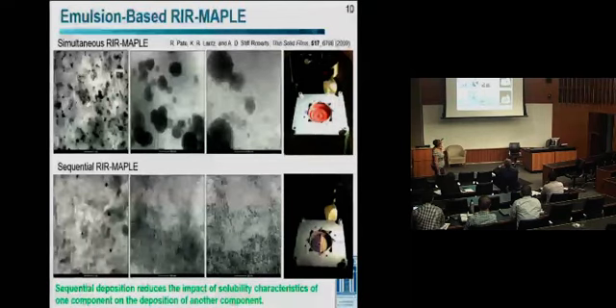But the other approach is what we call sequential RIR-MAPLE, where we partition the target. So you have one emulsion for your nanoparticles, one emulsion for your polymer. The laser rasters across the target as it rotates, and you get a completely different morphology of your films. Much more uniform dispersion, and these are the same size ranges, so 1 micron, 100 nanometers, and 50 nanometers. So having this control over the morphology in these hybrid organic-inorganic nanocomposite films.